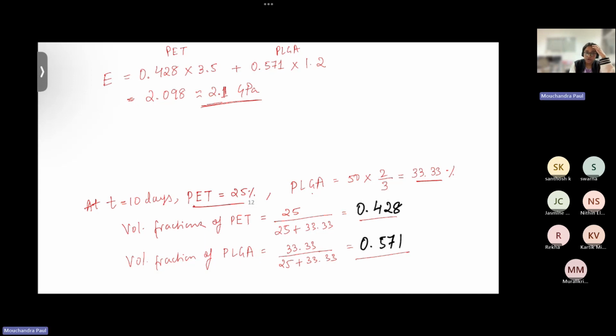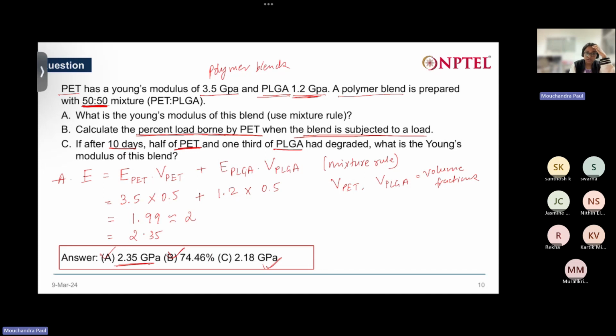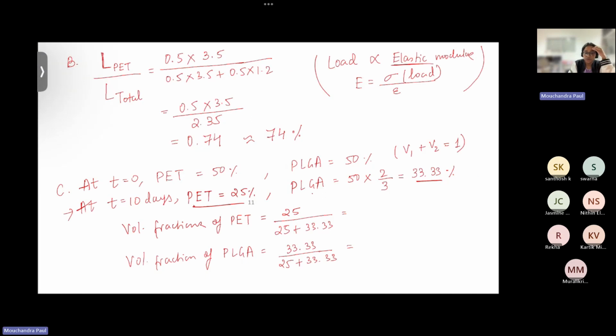Okay. So have you understood now how this type of problem is solved? What we did, we used the mixture rule to calculate the Young's modulus of this blend first. Then we were asked to calculate, if some load is given to this polymer blend, how much of this total load will be experienced by PET. And similarly, we can find how much load is experienced by PLGA. So for that, we took a ratio of basically the elastic moduluses that we got. So we know 50% of the blend is PET, and so how much load can be experienced by this PET content? It will be 50% or 0.5 into 3.5.